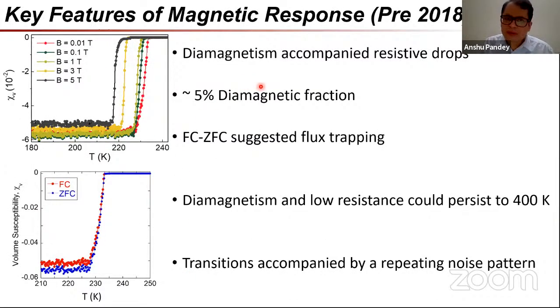So if we look at the magnetic response of these materials, we found that there is a diamagnetism which accompanies these resistive drops. Over here, we would prepare a single stock of material, essentially split it for two types of processing, one for films, one for making pellets. And what we found out was an approximate 5% diamagnetic fraction seemed to be there. We also obtained some data which seemed to suggest that there was flux trapping. So there was field cooled and ZFC data as well.